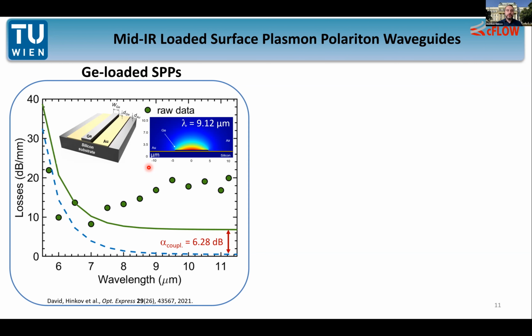This can be changed by using a concept which is called the loading concept. It's usually called dielectric loading if you use a dielectric material, or semiconductor loading, as it is here for our germanium loaded waveguides. So we change the geometry a bit. We have the substrate and in this case a gold layer as a metal, but now we add a slab, as we saw before in the dielectric waveguides. We add a slab of germanium on top of that, which now helps, because germanium has a higher permittivity than the surrounding air, to confine the mode towards the surface.